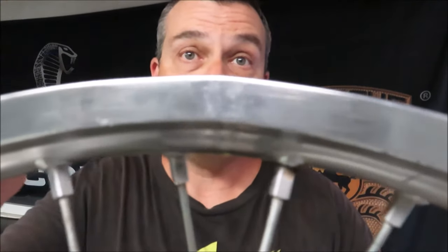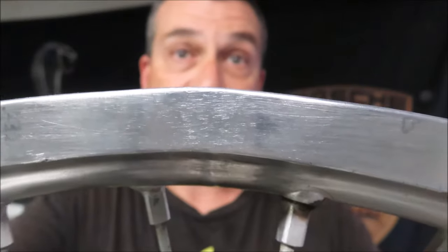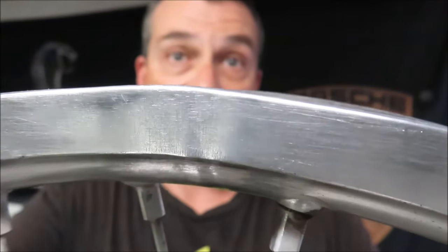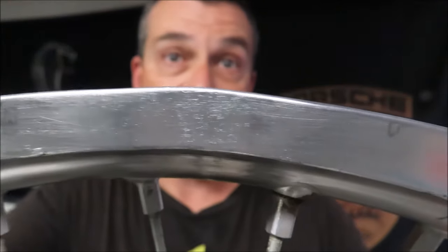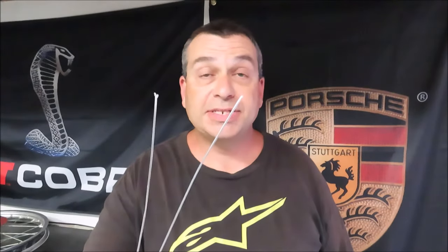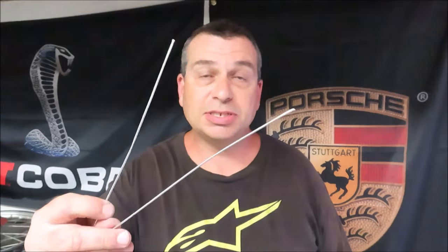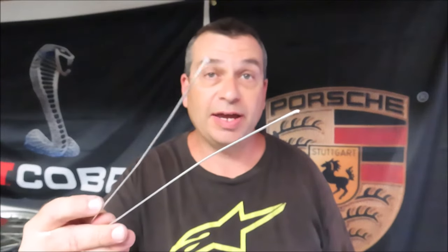But in doing so, it actually sealed up the crack. But none of the welding rod melted in to fill in the crack. It was just the wheel coming together on its own. But as you can see, the crack is gone. There's no evidence of it. Well, that was my attempt at fixing an aluminum motorcycle wheel with a small crack using these aluminum welding rods I got off of Amazon. It didn't go according to plan, but I did get the crack sealed up.